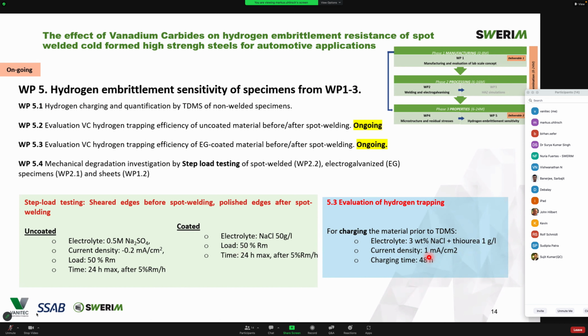So we wanted to check in this work whether spot welding is a threat. But in fact, our results indicate that, of course, the conditions we use now are not in-service conditions, it's lab testing conditions. It is a strong indication that spot welding might be a possible threat for these high-strength steels, definitely.